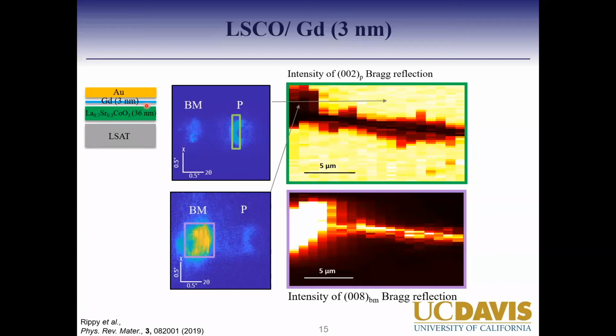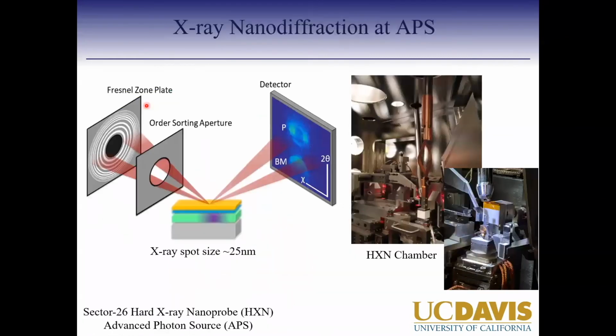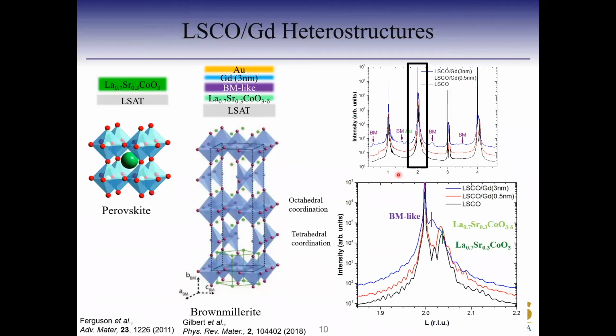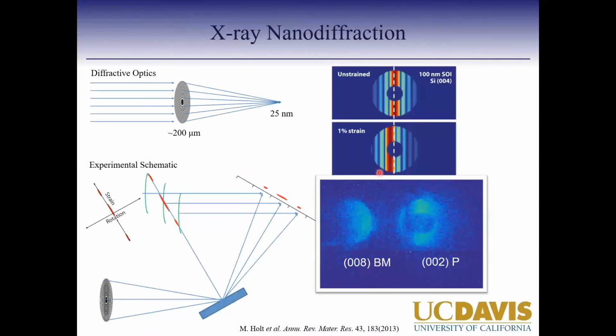Right. So the point is, it's hard to get to a Bragg peak at lower angles. If I go back to the XRD, this one is at about 18 degrees or so. It can actually be a high angle Bragg peak. You just need a low angle of incidence. Right, so you're saying grazing incidence X-ray diffraction to do that. Yeah, we haven't tried that, so that is something we can try.